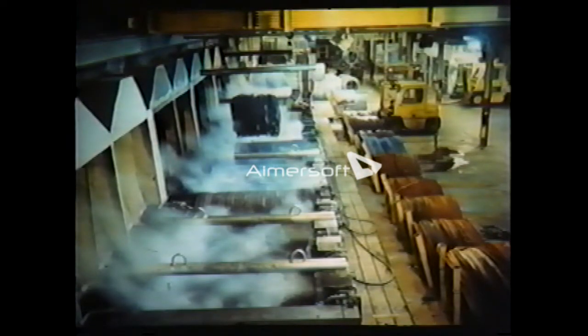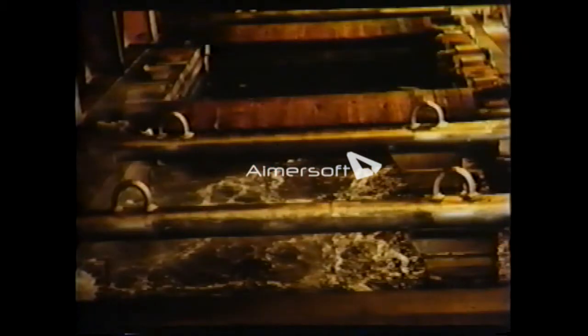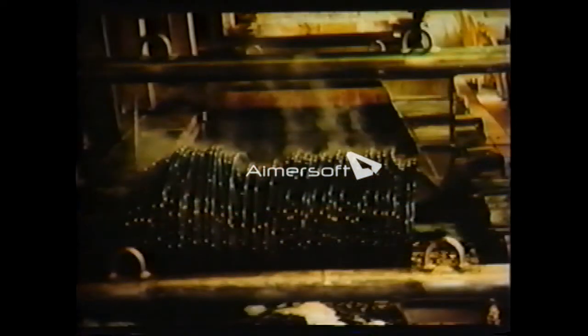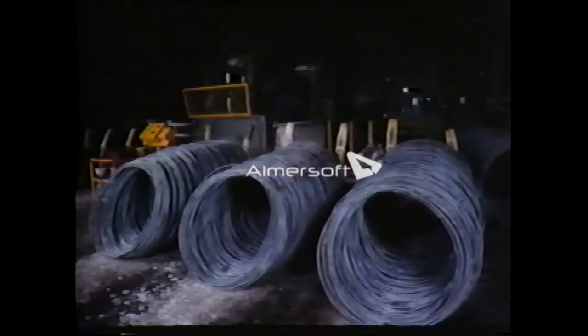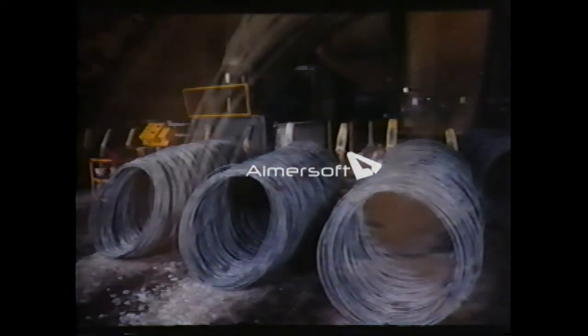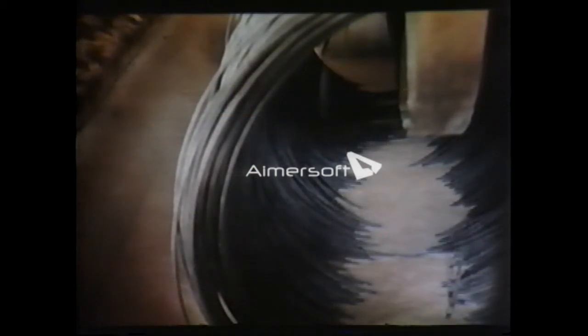Pickling cleans the coils by suspending them in a solution of sulfuric acid and water. To remove as much acid as possible, coils are rinsed with water. They then receive a heavy lime coating. The lime neutralizes any remaining acid and protects the raw material should it not be used immediately. It also acts as a vehicle to pick up a dry lubricating compound used later in the bolt-making process.